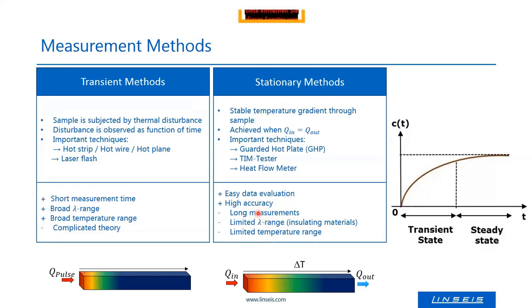The plate instruments or steady state instruments are suitable for the low thermal conductivity range. For good conductors, it's difficult because you have to avoid heat loss during the experiment. You have to insulate everything very well. And at a certain thermal conductivity, you cannot avoid heat loss anymore, and by that, the range is limited.